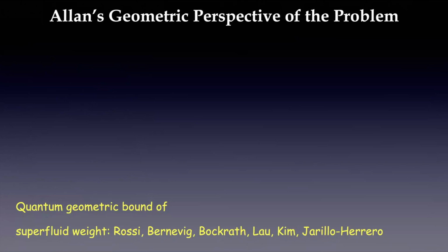It's still the same problem. In the past couple of years, people talked about twisted bilayer graphene superconductivity. The bands are really flat. Cooper pairs have very slow velocity. How can they superconduct? It turns out, people in the audience, Enrico Rossi and Andrei Bernevig, had a theory talking about how quantum geometry gives a strong contribution to the superfluid weight, and therefore superconductivity is rescued. My collaborator Ginny and Mark did a very beautiful experiment demonstrating that. And more recently, Phillips' group and Pablo's group have very direct measurements of superfluid density.